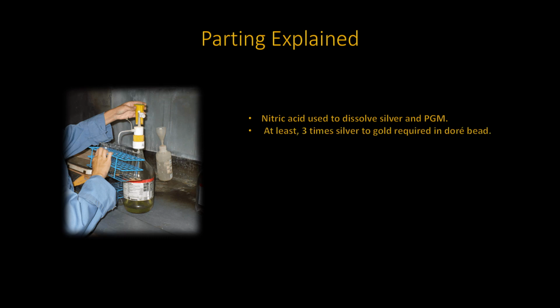As mentioned in presentation 16, to conduct a successful parting, the ratio of 3 parts silver to 1 part gold is required in the doré bead. Many textbooks will tell you that a ratio of between 4 and 6 parts silver to 1 part gold is best. Nitric cannot be used successfully if the ratio is less than 3 to 1. With a ratio of 3 to 1, it will require a stronger nitric solution with a longer continued heating to fully separate the silver from the bead.